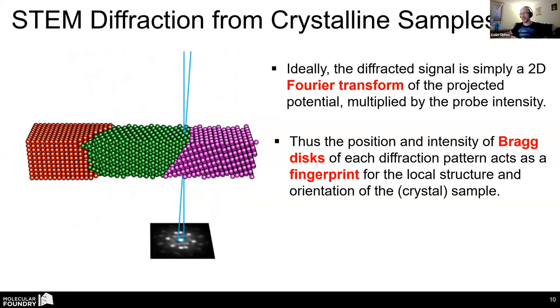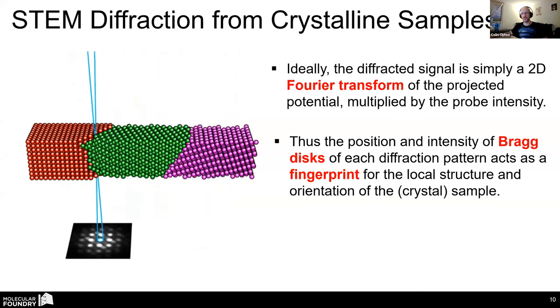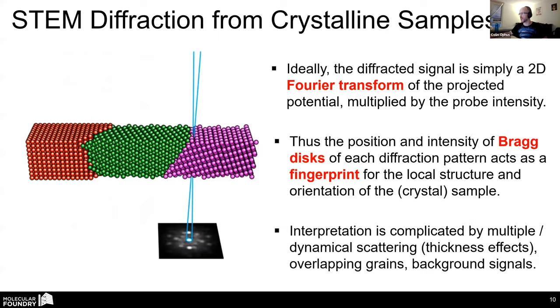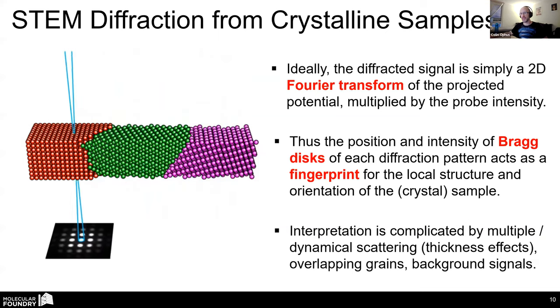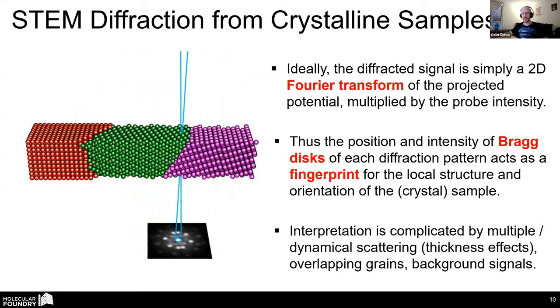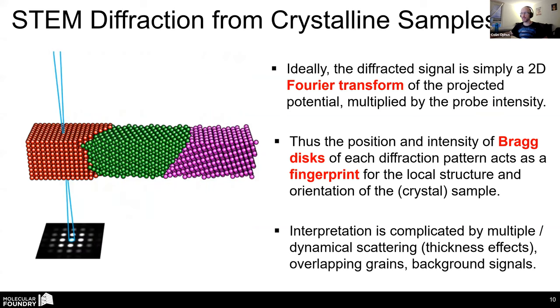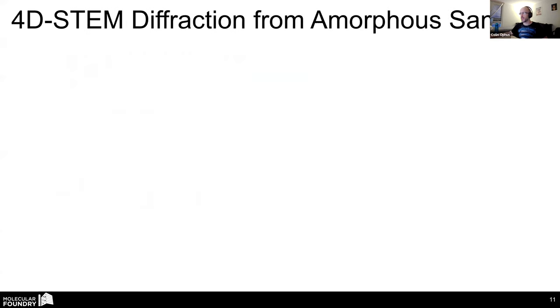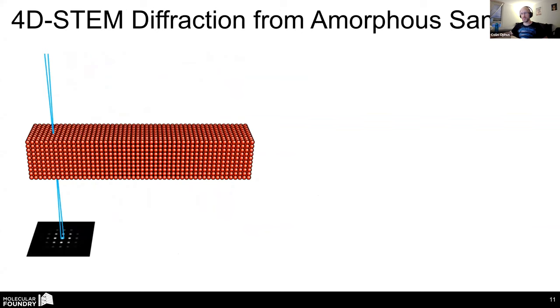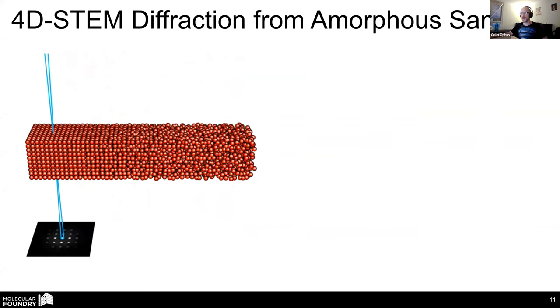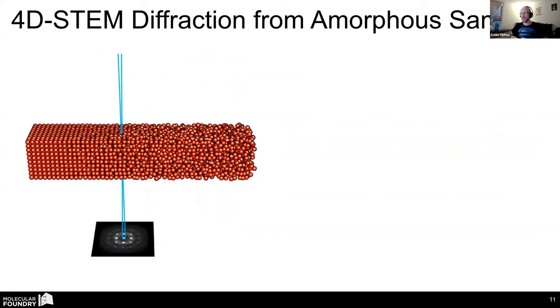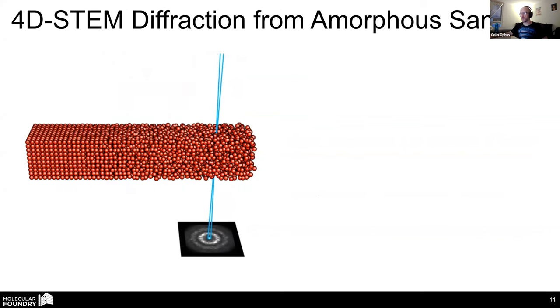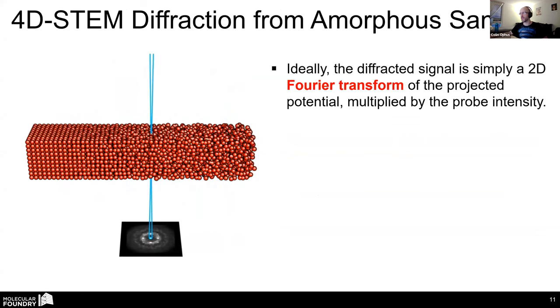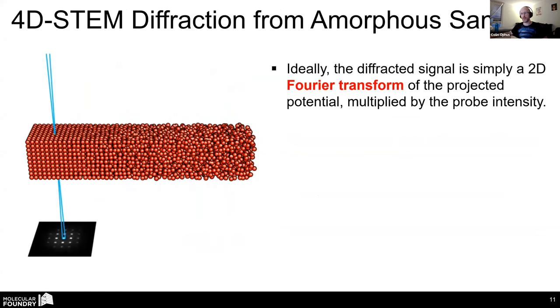And these patterns act as fingerprints for the local material, its orientation, its deformation, et cetera. Now, unfortunately, electrons scatter very strongly, so it's often complicated by multiple scattering of the beam. And I'll return to that later. For amorphous materials, you see something very similar. If I take this toy model and randomly displace all the atoms on the right-hand side and then scan through it, you can see we go from a nice square perfect diffraction pattern to these characteristic amorphous halos. But the interpretation of the pattern is the same.